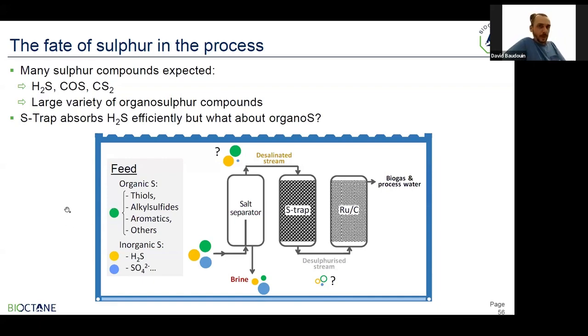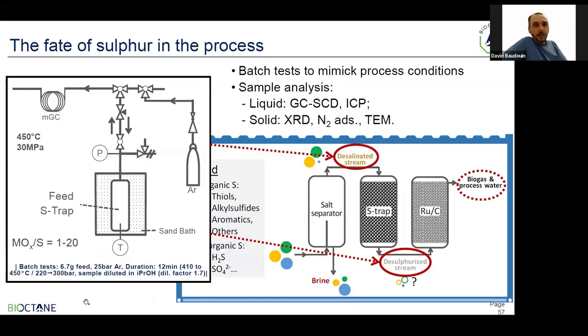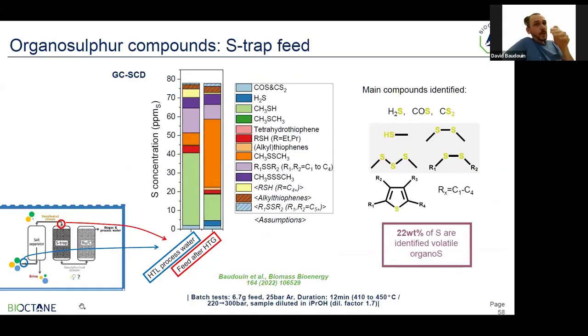So we put a good deal of effort into analyzing, identifying and quantifying the different compounds present in the stream entering the sulfur trap bed, and also the one not being trapped and not being converted and entering the catalyst bed. To do that, we did some batch tests to mimic the conditions observed in the continuous test. We also did continuous tests to confirm that the batch test was representative.